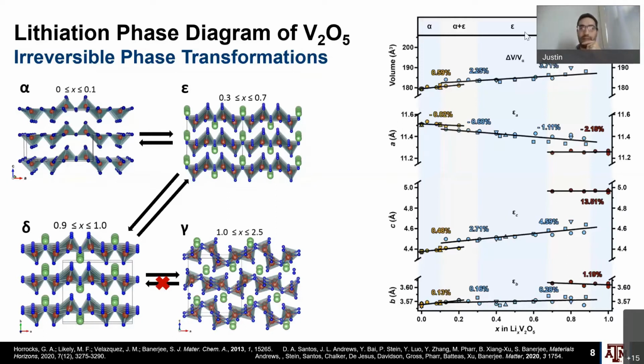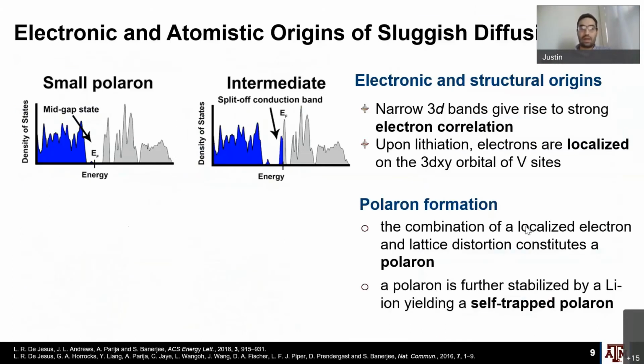And what's interesting about this material is, unlike a lot of layered cathode materials where the primary change in the crystal structure is just a change in either ordering or in the layer separation, this material actually expands quite a bit and contracts in different directions. So there's a lot of different strain that actually takes place and lattice mismatch between these phases that coexist in materials. And so this presents a problem that I'll talk about a little bit as well in terms of the mesoscale and some of the effects on capacity fade and things like that.